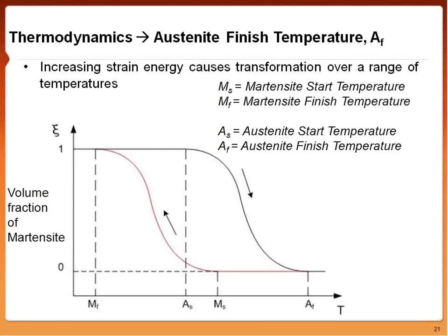So the increasing strain energy from the transformation causes that transformation to happen over a range of temperatures. And we don't actually go from complete austenite to martensite right away, or the other way around. We go through a series of stages where there are more volume fractions of martensite being populated when we look at either the heating curve or the cooling curve, when we're going from hot to cold and cold to hot.